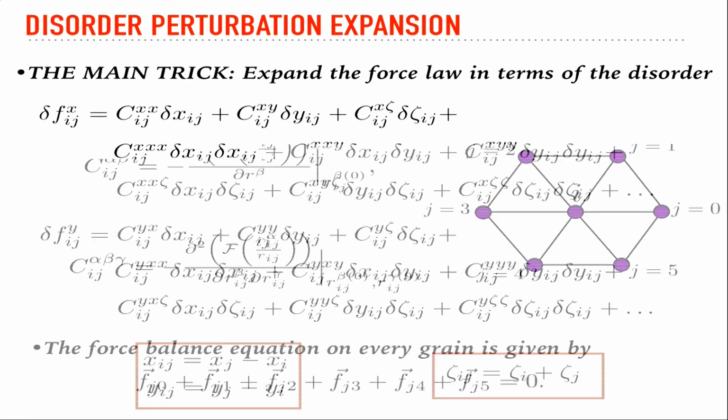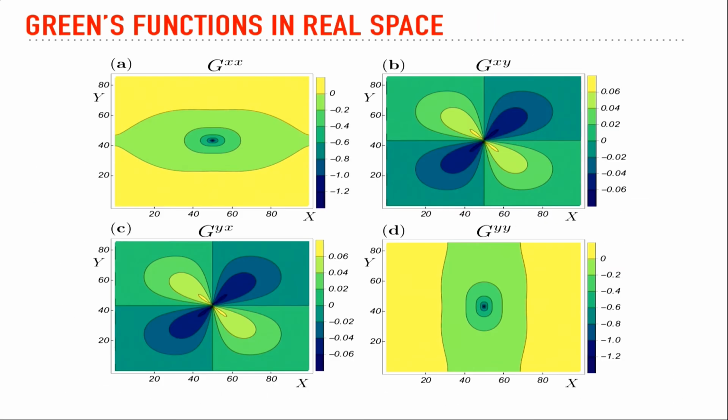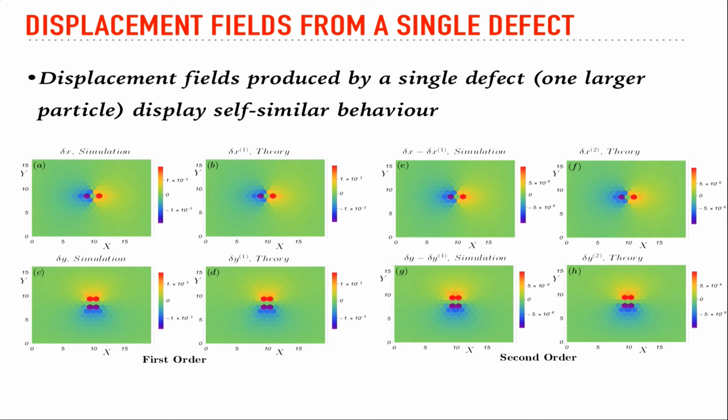Yeah, so this is another good question. Let me just point out that these techniques that I'm describing, at each order, so let me go back here, are all proportional to the size of the microscopic disorder. So for example, this effect that you're describing here at the first order is proportional to the size of the defect. This effect here is proportional to delta sigma squared, and so on and so forth. So the first order effect is proportional to delta sigma. This effect will occur at any small amount of size change, but this will scale linearly, and this will scale as a second order effect. So it depends on the resolution. Whether or not it becomes important is whether or not you can actually detect it. If the resolution of your experiments is fine enough, then you will detect it, even if it's a small change.